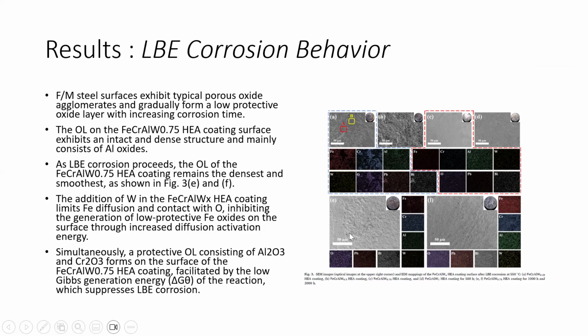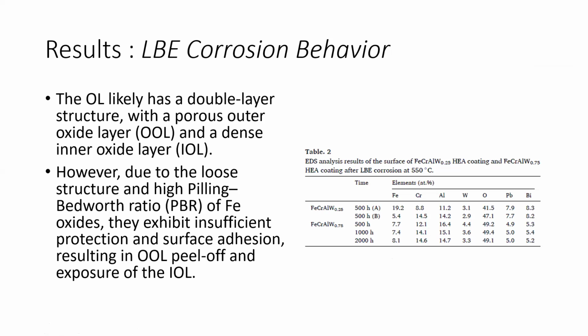The addition of tungsten in the sample coating limits the diffusion of oxygen, inhibiting the generation of low-protective ferrous oxide on the surface and thus slowing oxidation. Simultaneously, the oxide layer consisting of aluminum oxide and chromium oxide from the sample coating is facilitated by the lower Gibbs free energy of formation in contact with the surface LBE corrosion. The oxide layer likely has a double layer structure, with a porous outer oxide layer (OOL) and a dense inner oxide layer (IOL). However, due to the loose structure and the Pilling-Bedworth ratio (PBR) of the ferrous oxide, it exhibits insufficient protection, resulting in the OOL peeling off and exposure of the IOL.